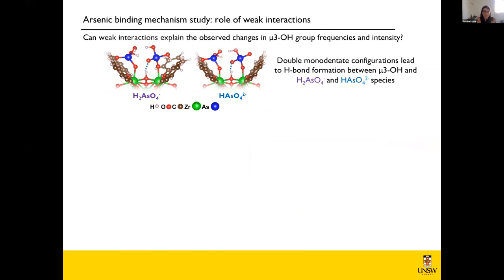Another thing we were excited to see is that this newly proposed adsorption mode with this double monodentate structure shows hydrogen bonding to this mu3OH group, which you might recall was indeed observed to be affected in the experiments. So this new structure also agrees with the experiments in terms of these IR observations.